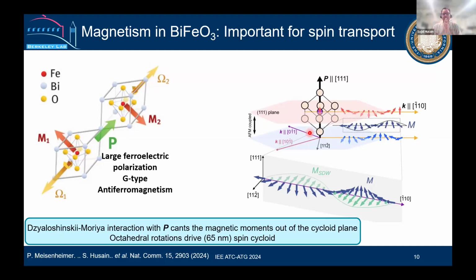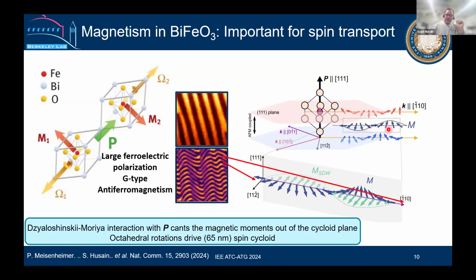So it has some spin ordering of 65 nanometers here on the right. Here on the right, in red and blue, they are two antiferromagnetically coupled spins, but because of the DMI, they are not completely parallel. If you see my hand, they are a little bit tilted, a few degrees in the plane, and that gives you some canted moment. And you can measure this canted moment using NV magnetometry. I will explain a little bit of that. So these are ferroelectric domains using piezoresponse force microscopy. These are magnetic domains. These are spin cycloids, we call them. Okay, so that's about the bismuth ferrite.